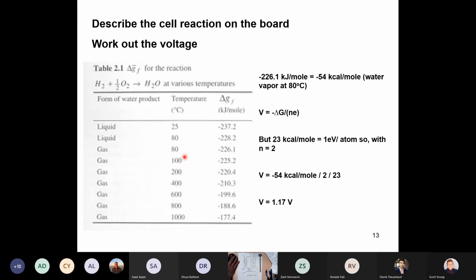And then as the temperature goes up and up, the voltage of the fuel cell will drop. And a polymer electrolyte membrane fuel cell can only operate up to about 120 or 125 degrees C. And then beyond that, they just don't work well anymore. And the main reason is that the membrane has to have water in it to have decent proton conductivity. And if you heat the fuel cell much above 125 degrees C, the membrane just dries out and it loses all conducting properties. So these other temperatures would be used for considerations like high temperature fuel cells, solid oxide fuel cells, or whatever the case may be.